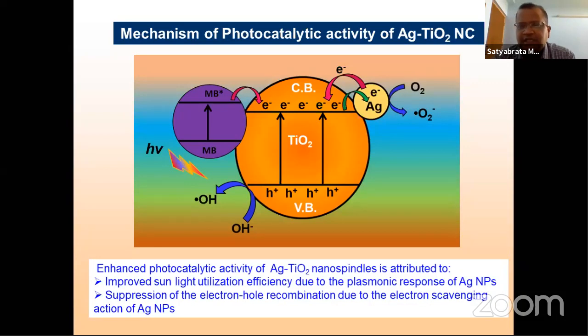Actually, in any coating, photocatalytic activity has a lot of contributions. One has to care about, when you have a thin film coating, what is the crystallite size? The first thing one has to worry about is the crystallite size and crystalline quality. So what is the fraction of amorphous or crystalline or different phases present? Second, what is the surface roughness of the film?